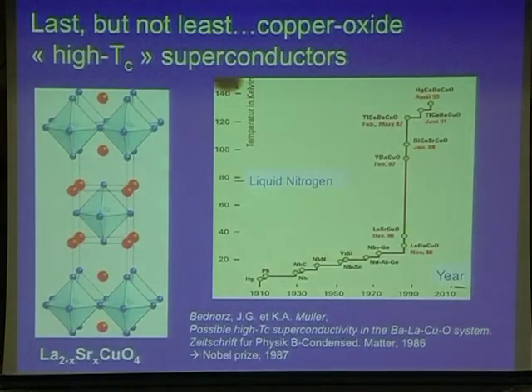Okay. Of course, there are much more spectacular examples. One of the most famous ones, which really rejuvenated this field in the mid-80s, is the discovery of a new class of superconductors that I already mentioned, which are the copper oxides, which completely changed our appreciation of superconductivity by boosting Tc from the 20 Kelvin range to very high temperature, not yet room temperature, but let's say a factor of 2 from that. So material science, to a large extent, has to do with factors of 2. If we could increase Tc by a factor of 2, this would, of course, bring a technological revolution.